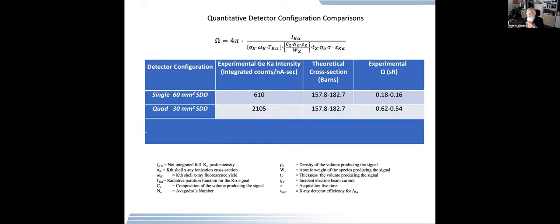Okay. Let's go to the quad detector systems now. Again, the same sample, measure the counts per nanoamp per second. We see the count rate has increased close to a factor of four, not quite. The solid angle has also correspondingly increased. We've gone from about 0.15, 0.2, upwards to around 0.6, 0.7, okay?